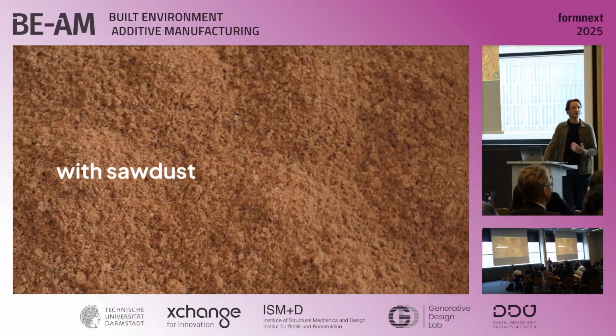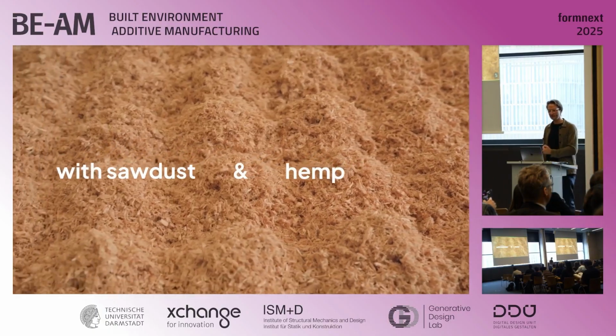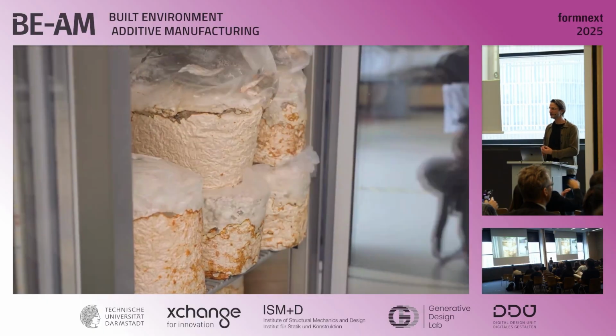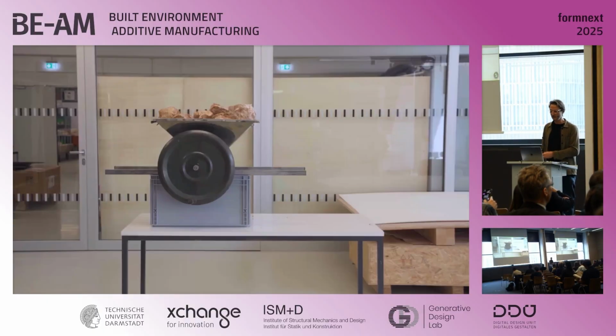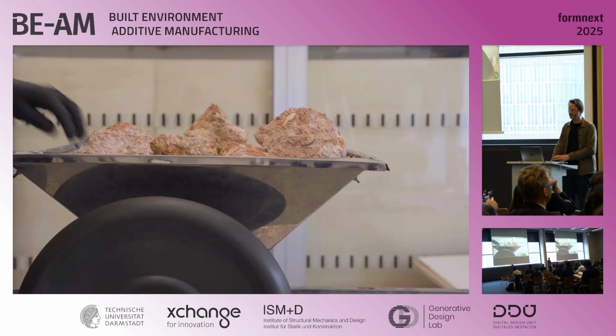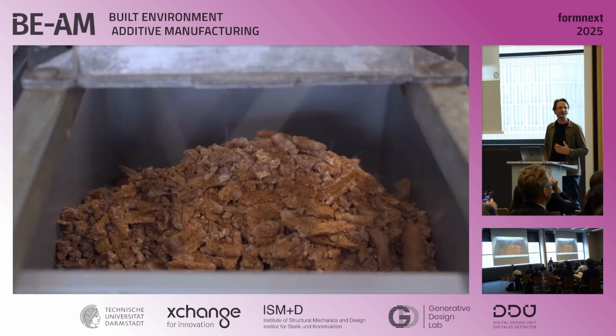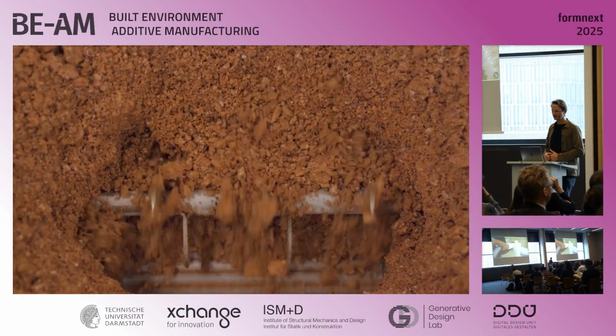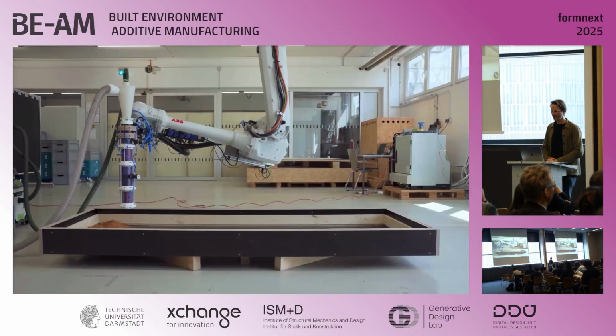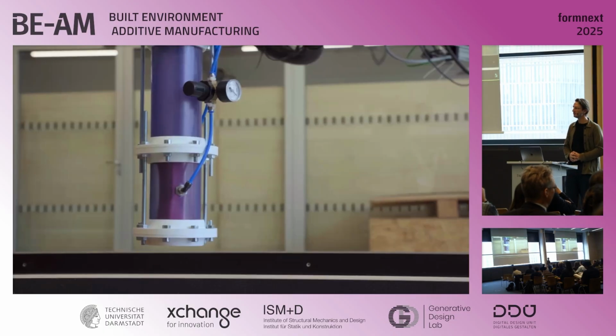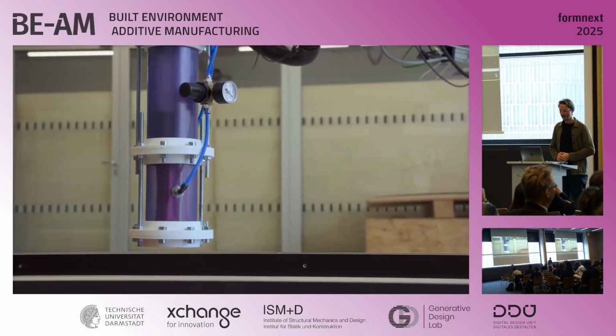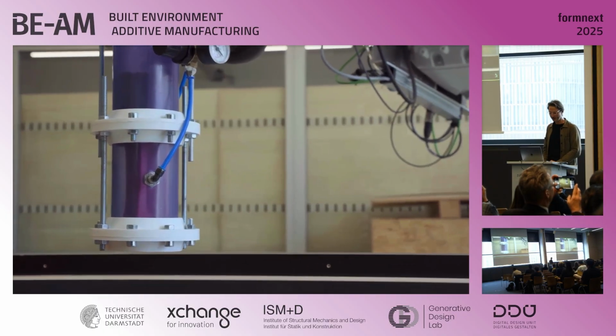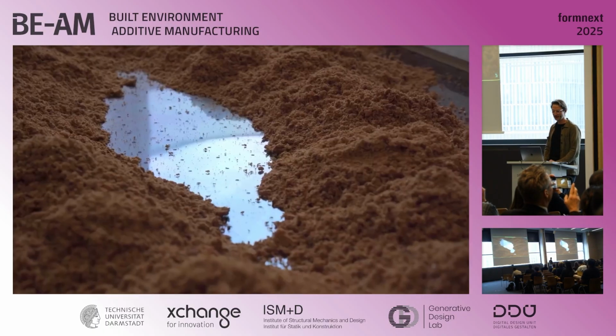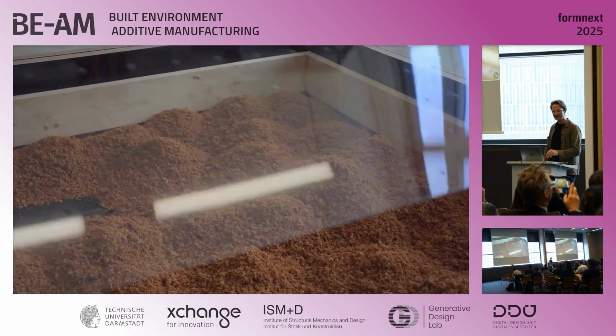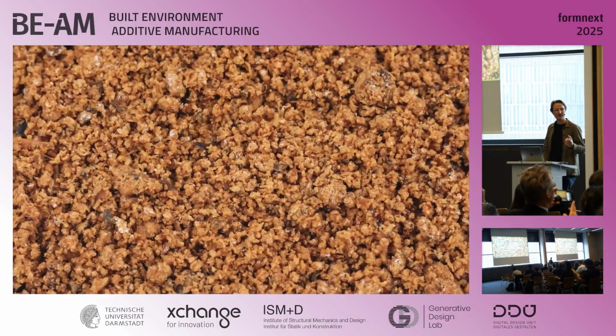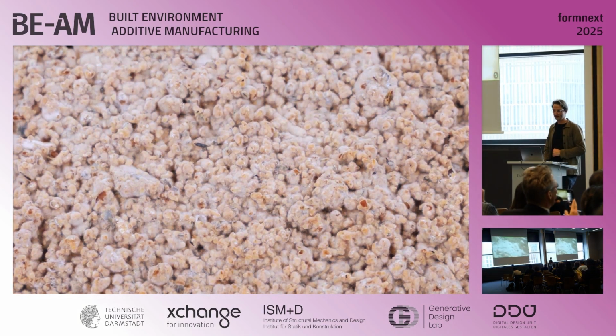The purpose is office partition walls, and we use one material with a high density to block the sound waves, that's the sawdust, and another material with a low density to absorb the sound, which is hemp. You can see there is still a lot of manual work. We have pre-grown mycelium, which we first have to shred, and then we developed a tool method that tries to minimize contamination and reduce manual handling. We developed a cyclone-based robotic tool where we can suck the material in and then deposit it where we want it.